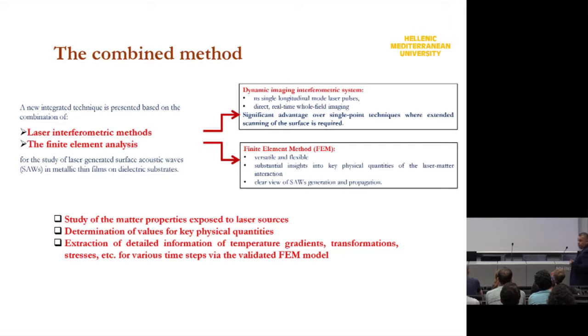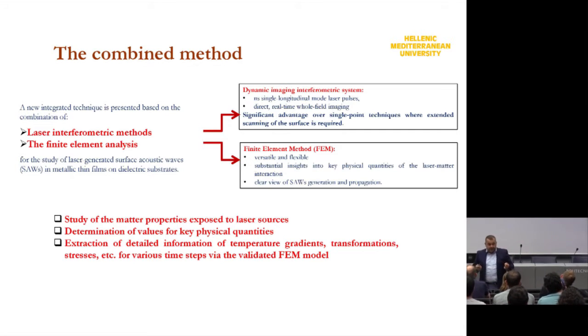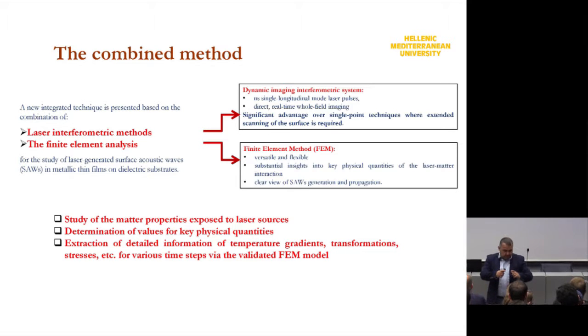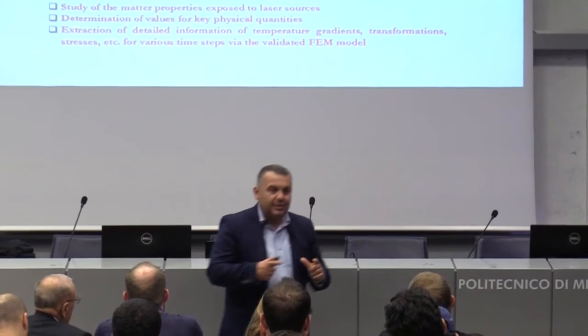So there is a combined method. We want to use an interferometric phase method to observe at once a big surface area of the material, and at the same time to be able to characterize vibrations on the order of nanometers. So we need an instrument to see the whole area and observe a one nanometer vibration at any point in the area. So this is actually the interferometric method.